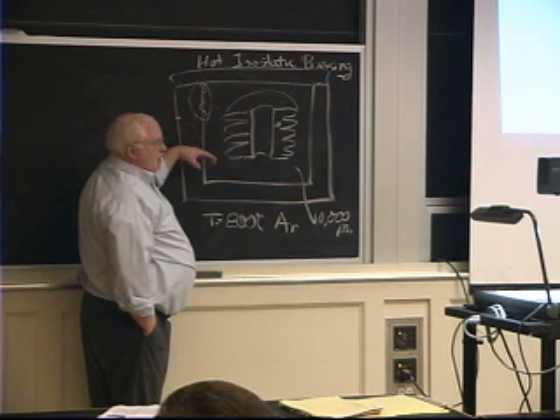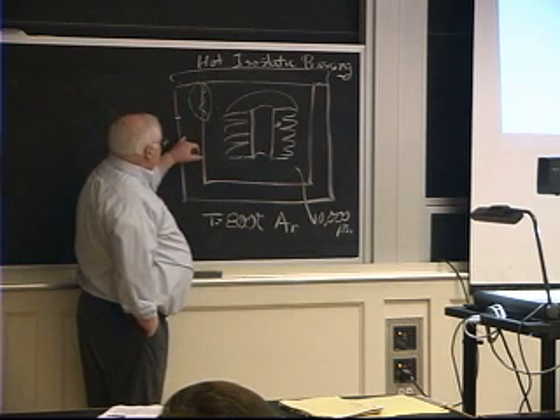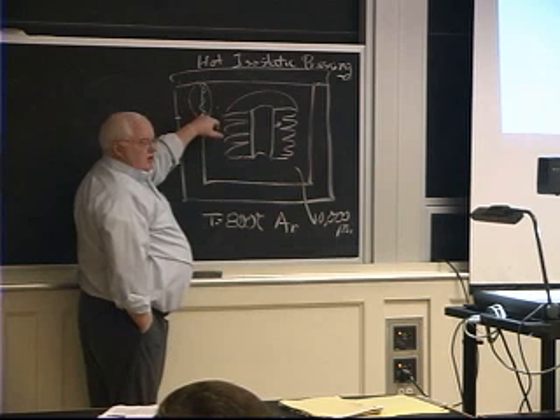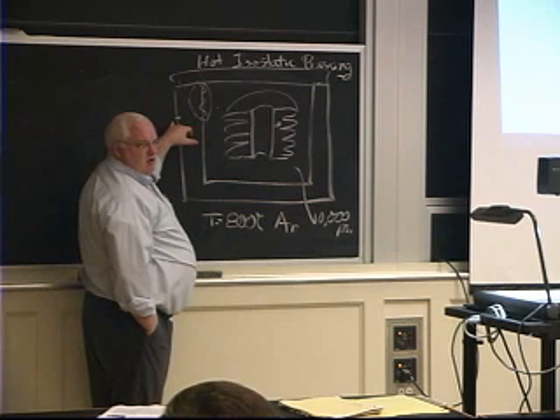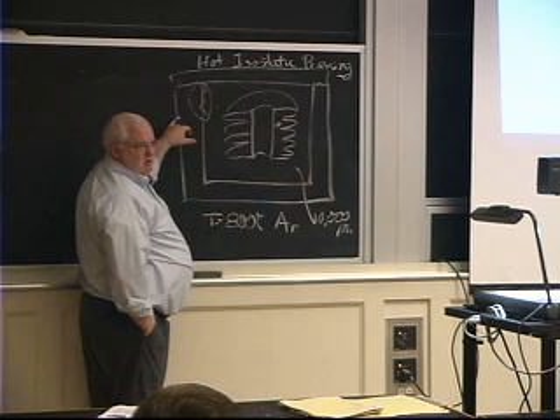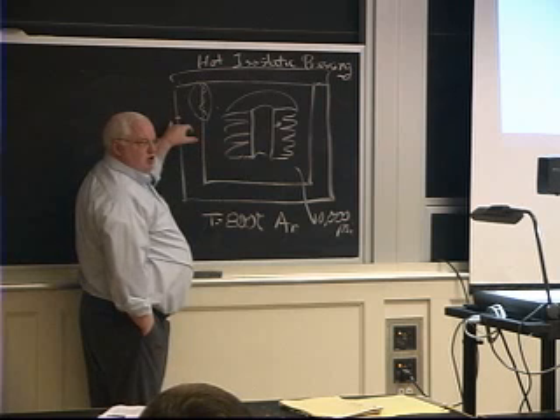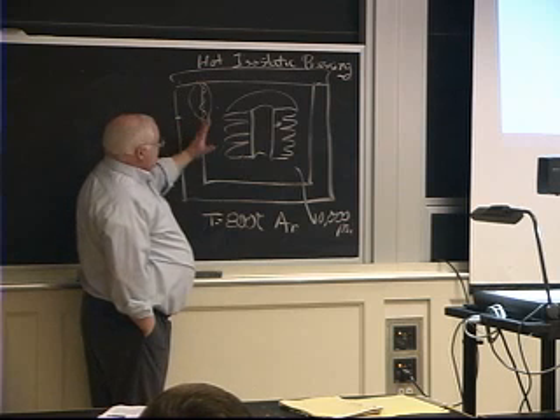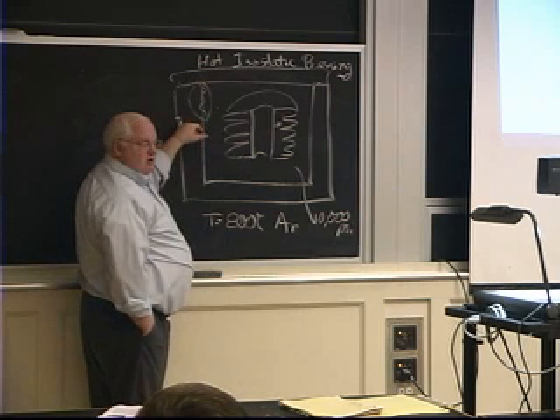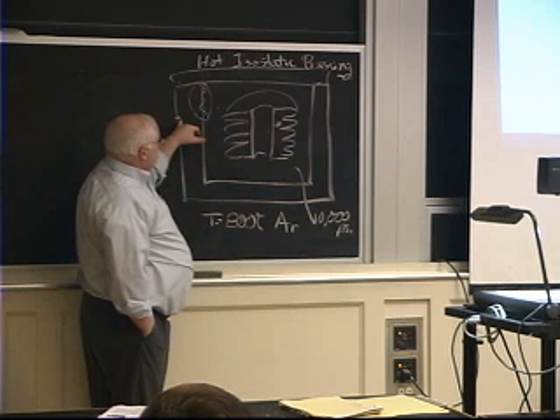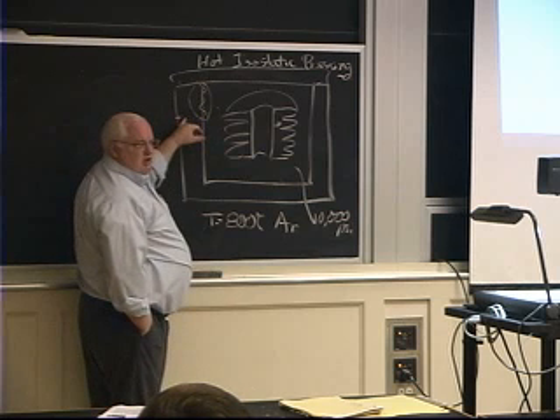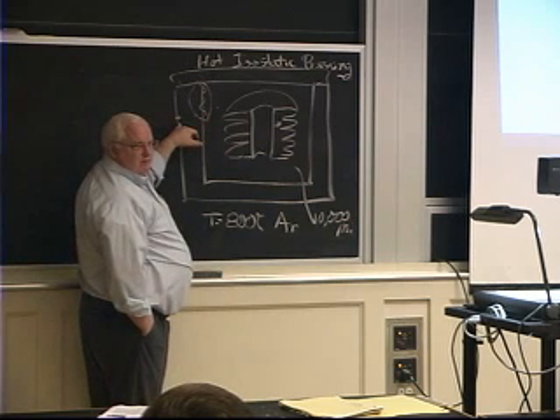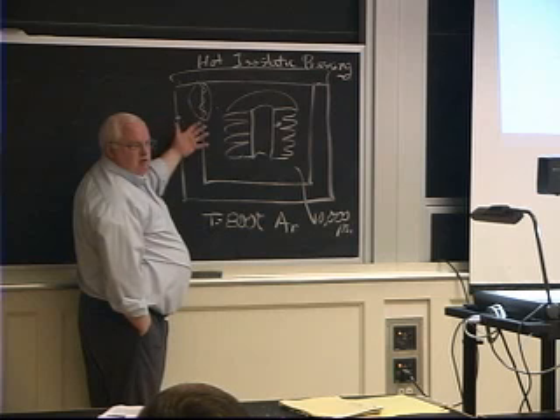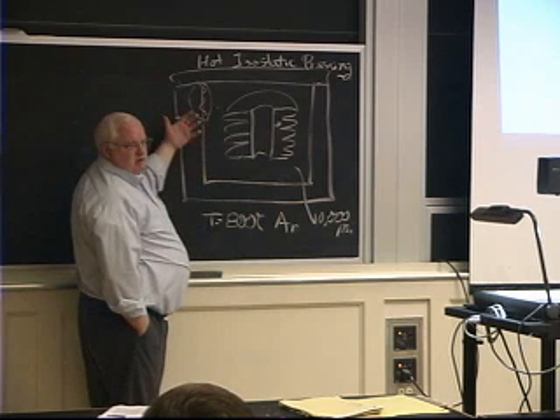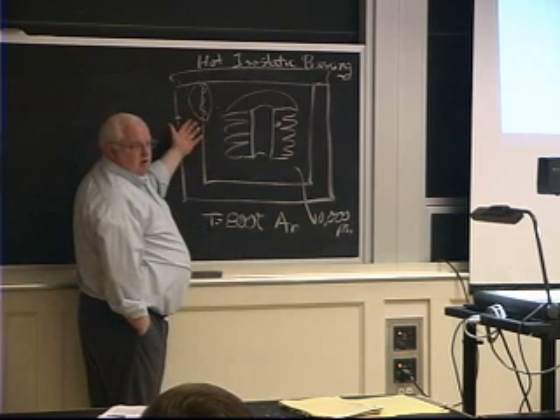Anyway, it's a long series of events, but the stress analysis was not done on the location where it failed, so they didn't worry about the stresses out here. It turns out it was transient thermal stresses. This thing being about 18 inches or 17 inches thick, where the fracture initiated, it takes 3 hours to get to temperature. This thing occurred after 2.5 hours. It was still seeing transient thermal stresses, which were higher than the operating stresses.